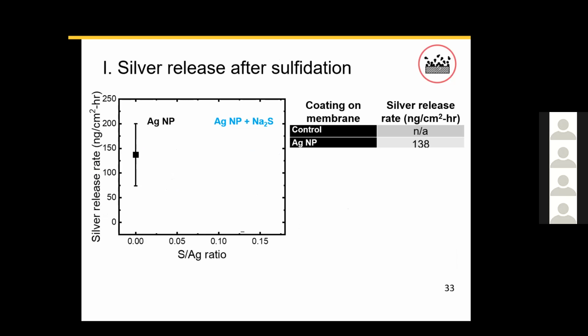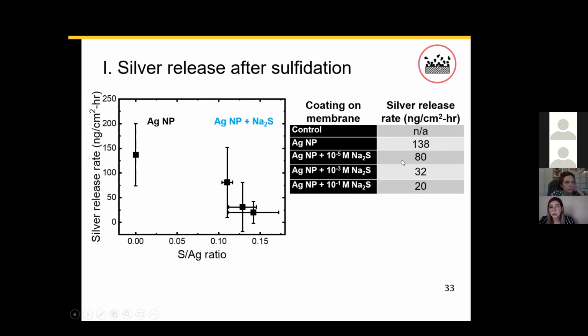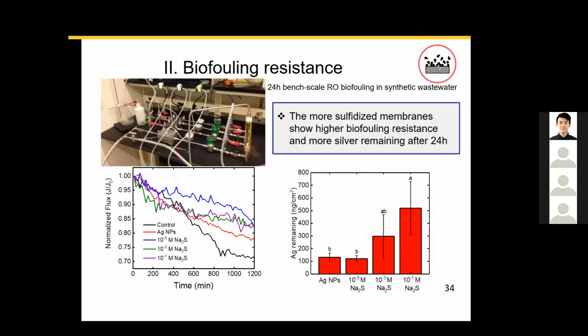The first thing that we wanted to make sure is that the sulfidation really slows down the silver release. We tested the silver nanoparticles, and we saw that the silver release was about 138 nanograms of silver per centimeter square per hour. But upon sulfidation, we see that the silver release dramatically decreases to 20 nanograms of silver per centimeter square per hour. That tells us that indeed the sulfidation step helps us slow down the silver release as we operate that membrane.